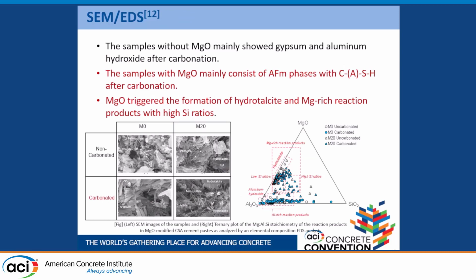So these are SEM images, and these are ternary plots of aluminum, magnesium, and silicon stoichiometry based upon EDS analysis. And from this SEM image, you can see the samples with magnesium oxide mainly consist of monosulfate and the CASH after carbonation. And based upon EDS analysis, you can see magnesium oxide mainly triggered formation of hydrotalcite and a magnesium-rich reaction product with high silicon ratios.